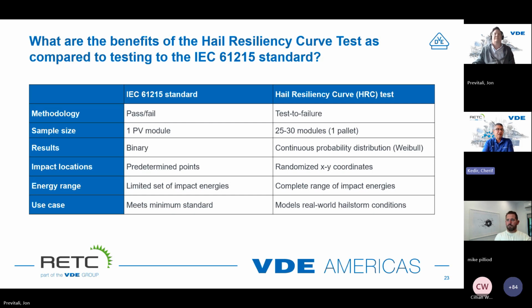And then, as JP mentioned, we just perform the test and we just keep increasing the kinetic energy until the module breaks. And that tells us the resiliency of that module. And then all of that data is collected and it's fed into the brilliant minds of our engineers at the VDEA team, and then an HRC is actually developed. The actual HRC curve is developed.